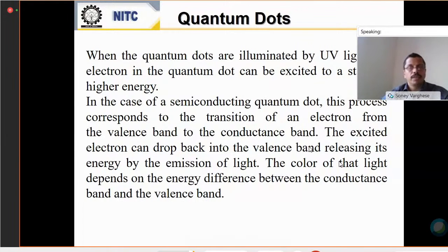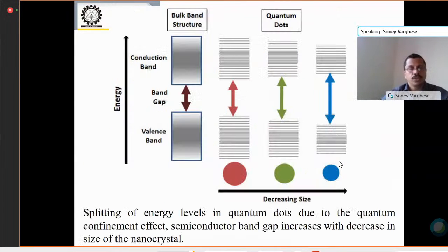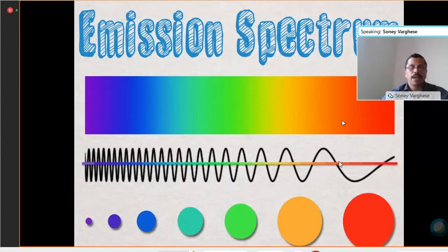When the quantum dots are illuminated with ultraviolet light, the electrons transition to the conduction band, and then when they de-excite, they emit light. So the color of the light depends on the band gap, right? Most of you are familiar with that. And you can see that as the size of the quantum dot decreases, the band gap increases, right? So that's what is shown here. And we can see the size dependence of color, right?